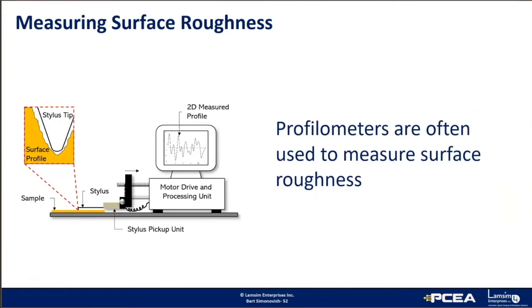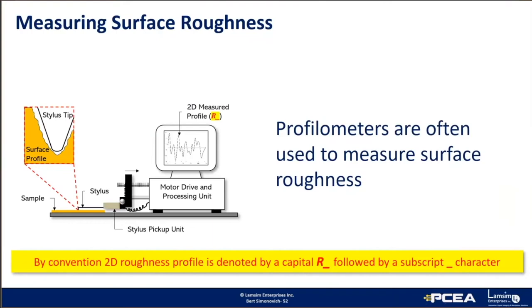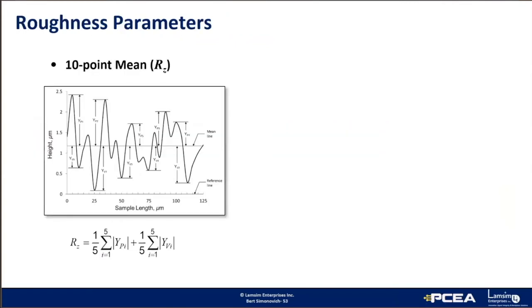Profilometers are often used to measure surface roughness. This process involves dragging a tiny stylus tip across a test sample where the 2D roughness profile is recorded. And by convention, every 2D roughness profile is defined by a capital letter R followed by a subscript. The subscript then identifies the formula that was used to report the roughness.